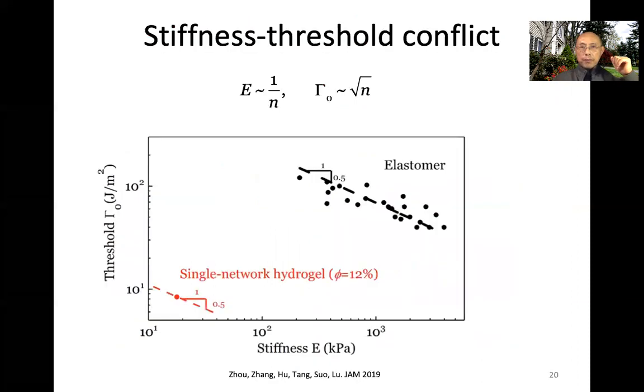All right, so here's another story related to fatigue. One idea of enhancing fatigue, coming from the Lake Thomas model, is you increase the chain length. This little n is how many monomers between two crosslinks, and fatigue threshold scales with the square root of n. Then you ask why people didn't know this. Of course, people know this. But if you make a material with very long chains, your elastic modulus, Young's modulus, will decrease because Young's modulus scales with 1/n. So there is a stiffness threshold conflict in the material.